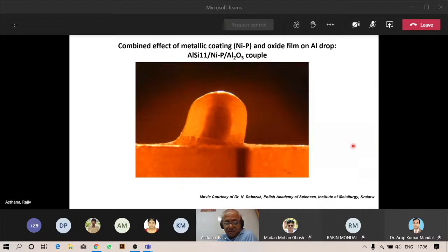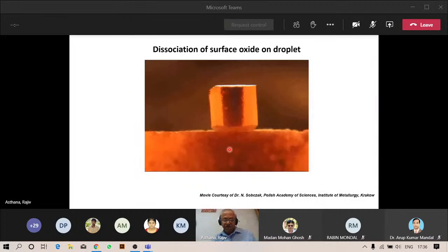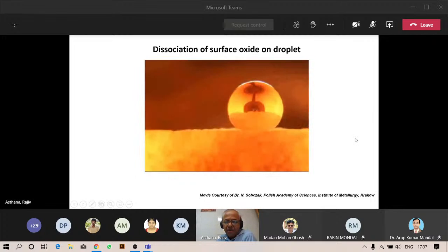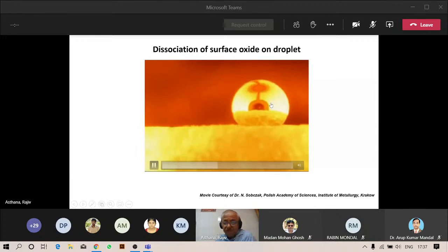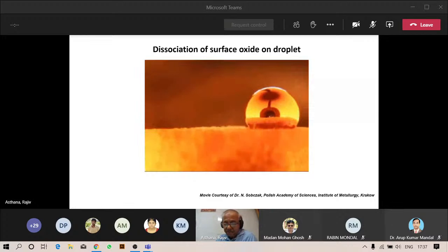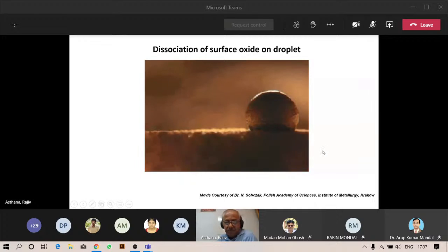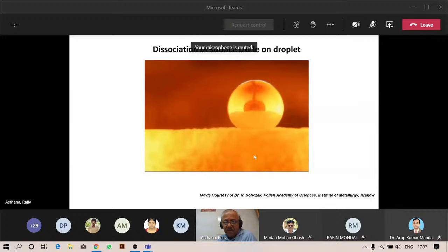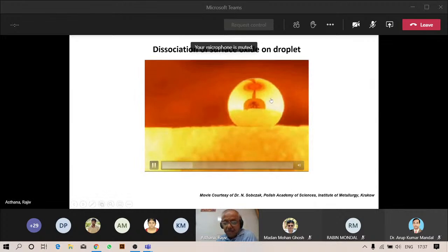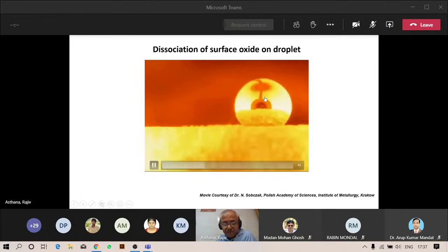But under high vacuum and under certain conditions, the oxide can actually dissociate and it can allow for spreading to take place. Let's see here if I can get it to move. You will see the oxide on the droplet breaking apart. You see the pieces of oxide breaking, and the shiny droplet you can see because you can also see the imaging camera on the droplet here. And of course, this is during the cooling process here. This is what you see here. The droplet has oxide which broke off. These kind of experiments are pretty difficult to conduct because you have very high vacuum system and you want really controlled temperatures.